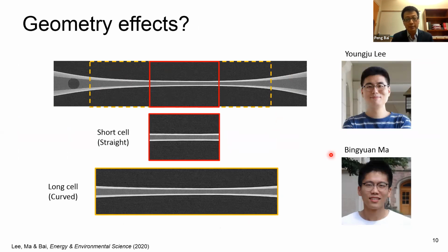So when my student Bingyuan Ma tried to study the sodium electrolyte system, the sodium metal system, he found out that, because of the electrolyte, you can push the metal right to the middle part so that it's almost straight. And if you change to another electrolyte, you can only push to the tapering part, so that we got two types of geometry. One is the straight channel, the other one is the curved channel. So this is the way we started the geometric effect. And based on that, Youngju Lee carried out a systematic study to verify our hypothesis. So I will introduce now our discovery.